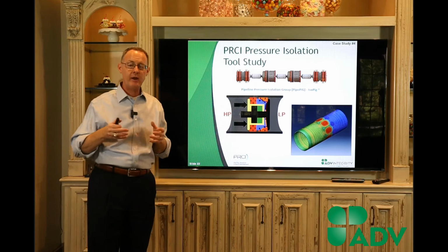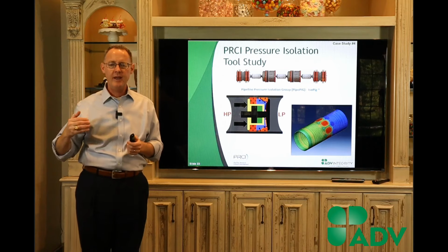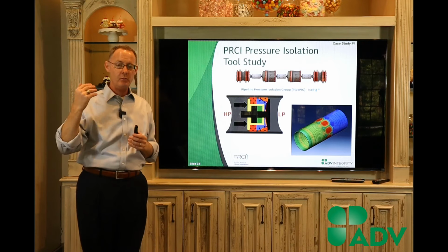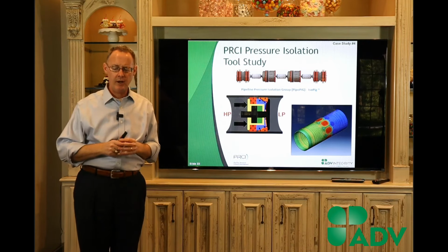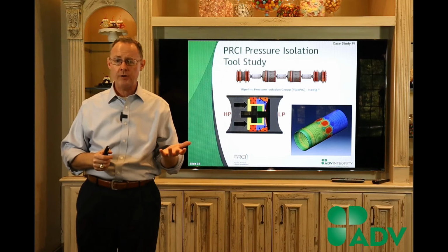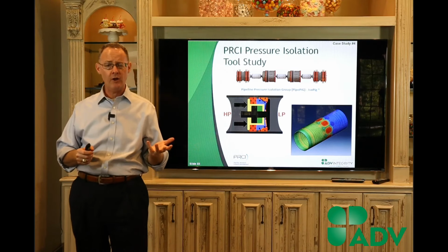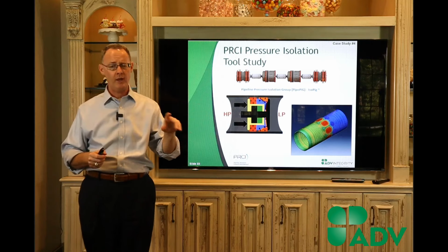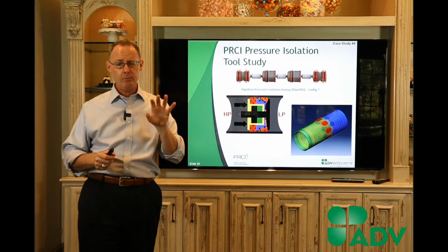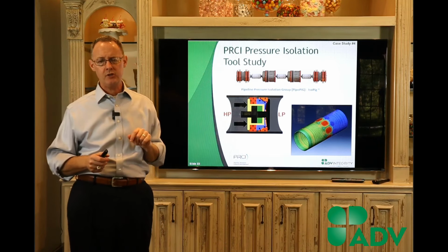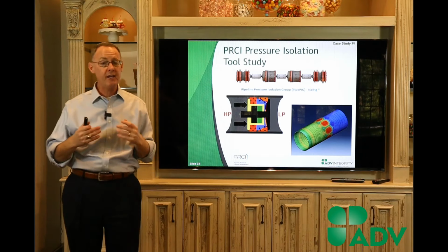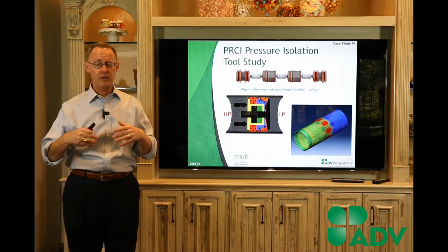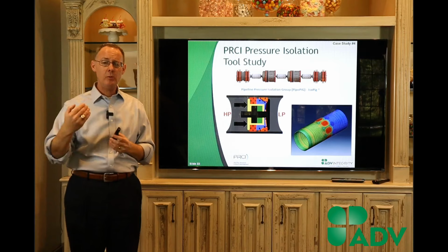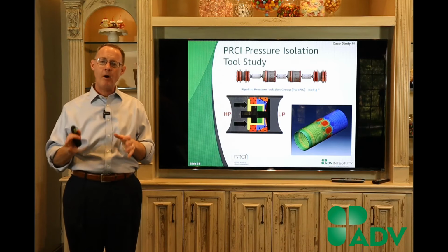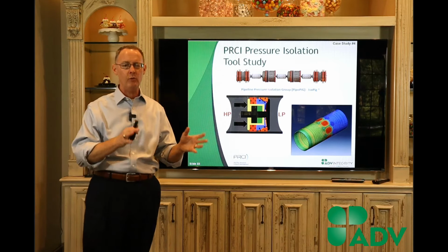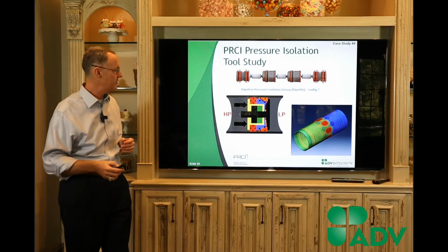And so you've got some areas where you have some elevated stresses, but to me, the thing that was very beneficial in this, and I'm going to give David a lot of credit, we started off, we did FEA models to try to understand it, and we had 3 technology companies who were extremely helpful. We had TDW, Stats, and PPIG, which is a pipeline pressure isolation group. All 3 of those companies contributed financially, contributed their time, and contributed their expertise. And what we found was the models were actually very accurate relative to what we measure with the strain gauges.